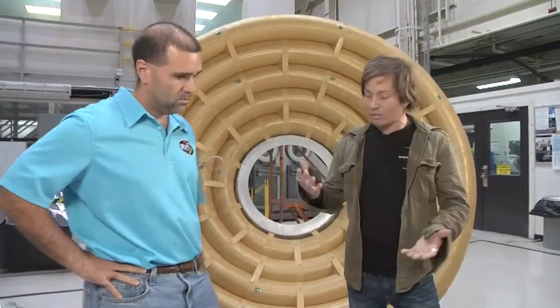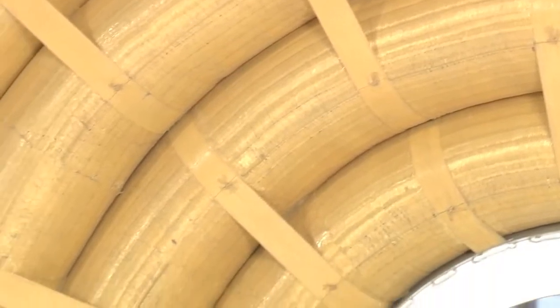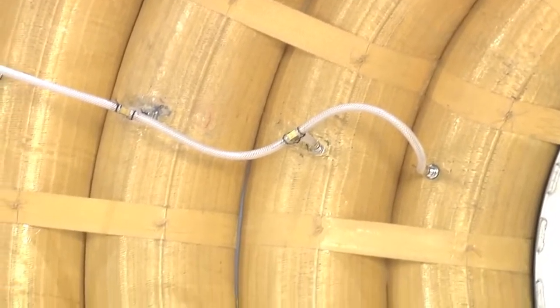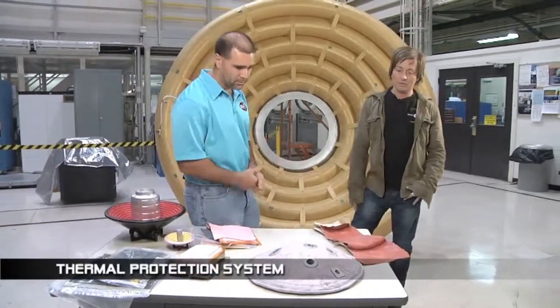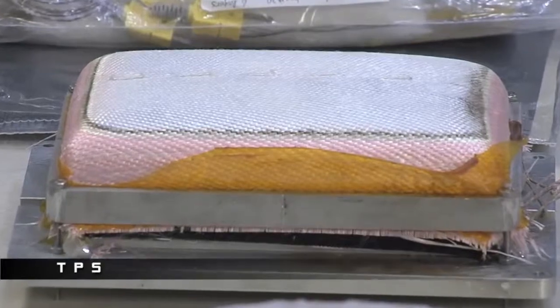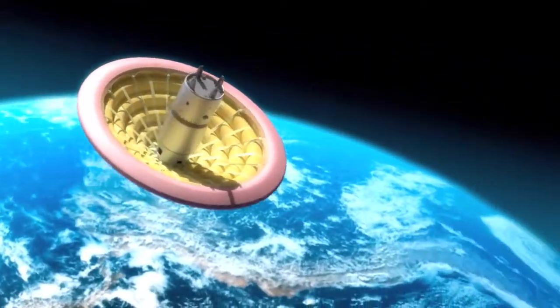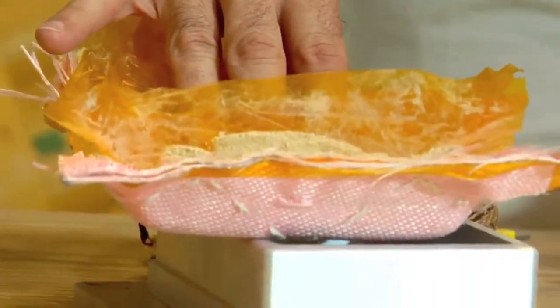Are these single layers or do they have multiple layers? We actually have two distinct assemblies. The inflatable structure gives the aeroshell form, the drag area, and survives the pressure load and aerodynamic forces. But that can't survive the heat of reentry, so we have to protect it with a thermal protection system — TPS. It has an outer ply that survives the high heat of entry flow. Then an insulating ply that knocks the temperature from the outer surface down to something the back surface can survive. And then a gas barrier which prevents gas from being drawn through the fabric and bypassing the insulating layer.